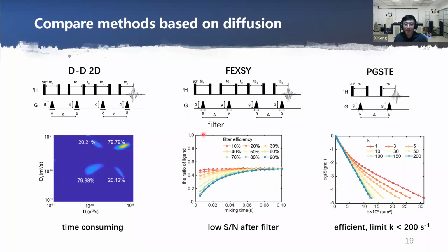So I tried three different methods to measure ligand exchange. The first is the diffusion 2D correlation with two stimulated echo blocks. The exchange rate can be obtained from the cross peaks of these two diffusion species. But the 2D method is very time consuming. For a single plot, we need many hours.